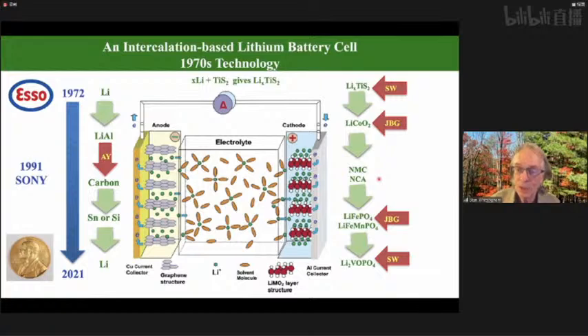Sometime later, John also came up with the idea of using the phosphates, in particular lithium iron phosphate. It cycles very well, and this was really the work that Yet-Ming Chiang and A123 did to commercialize John's idea, but it only has about half the energy density of the NMC. So it's interesting for some applications, but not for most mobile ones.